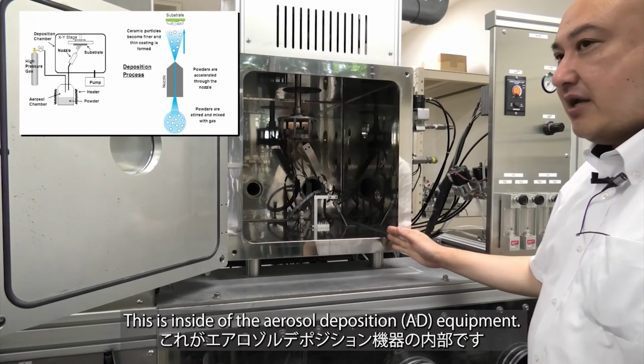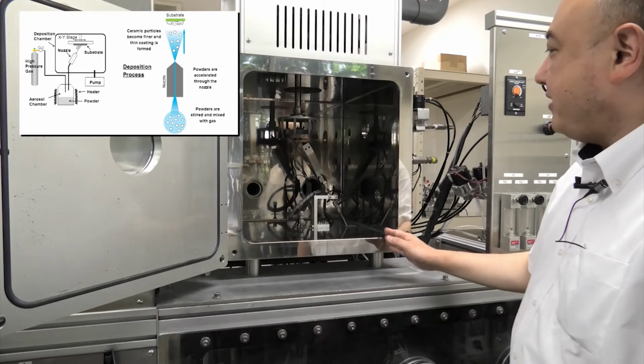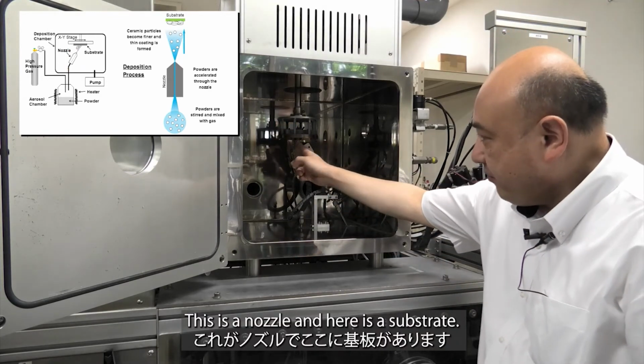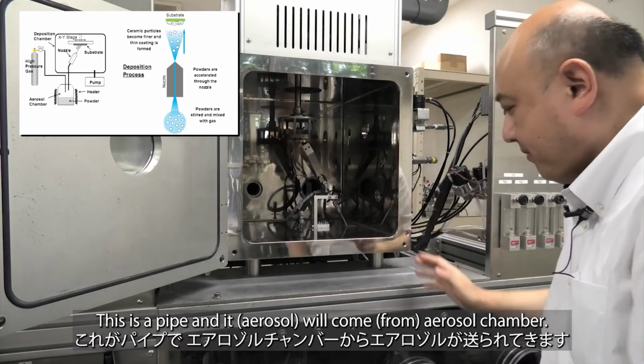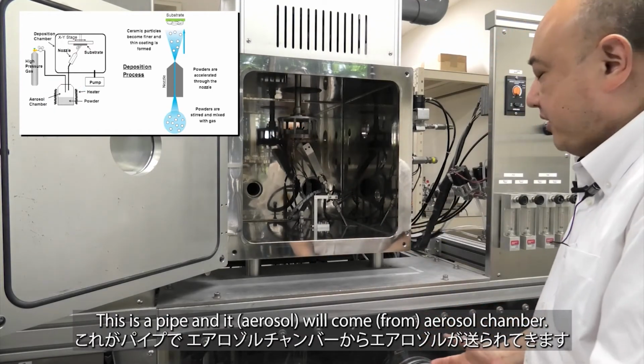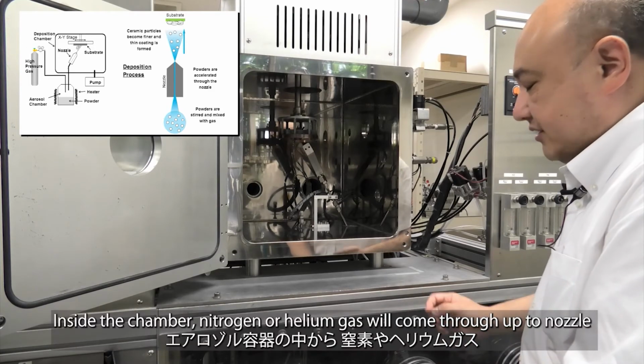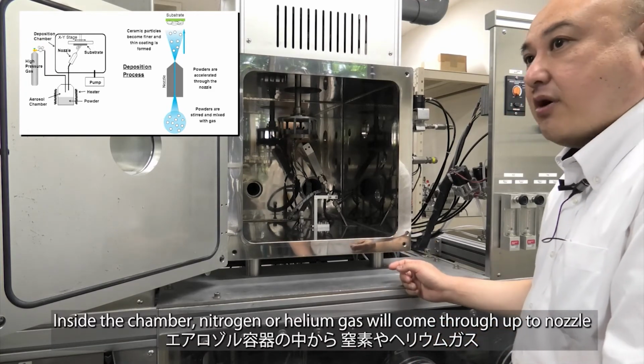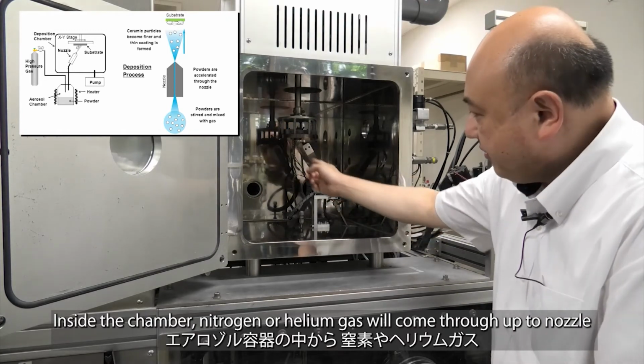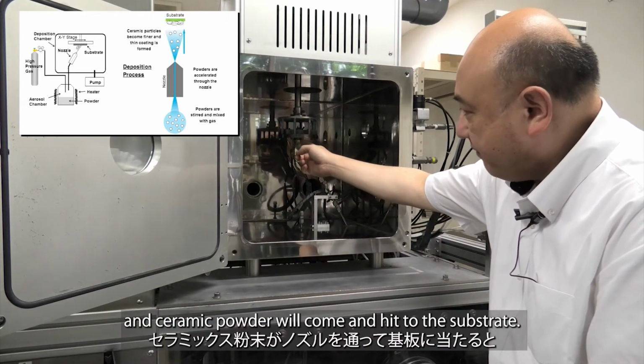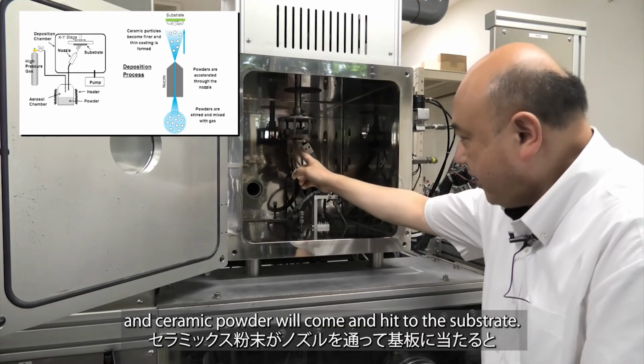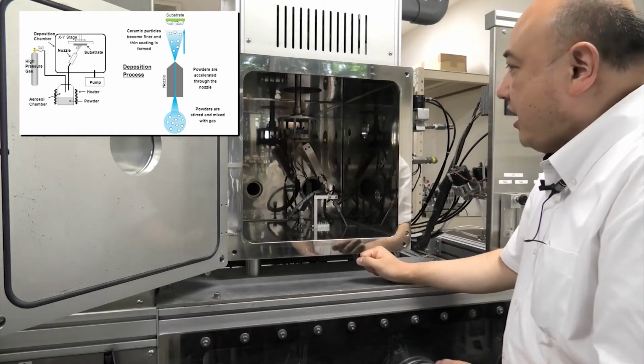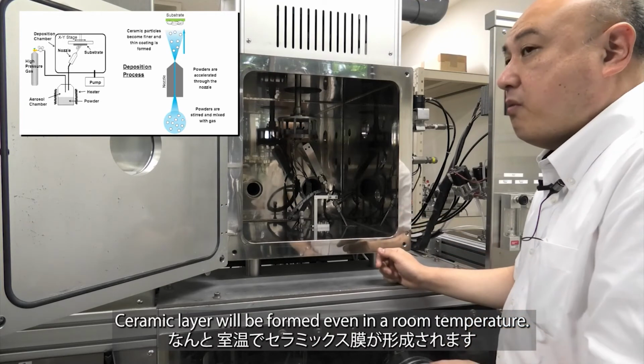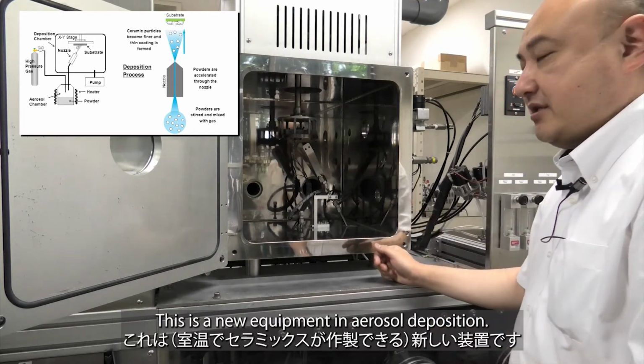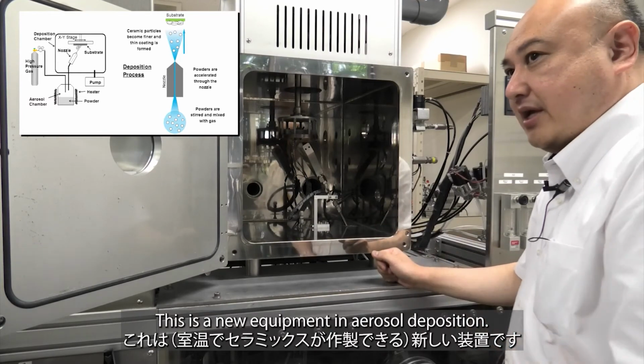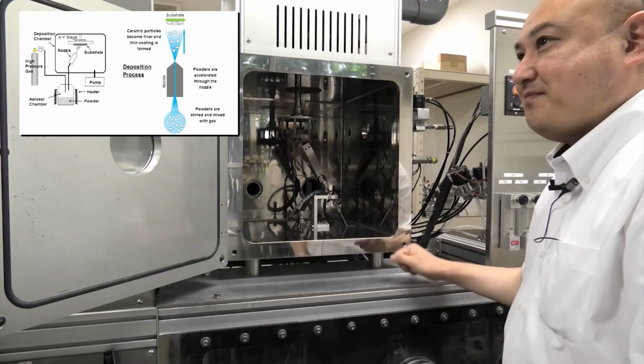This is the inside of the aerosol deposition equipment. This is a nozzle, and here we have a substrate, and this is a pipe. Nitrogen or helium gas comes into the aerosol chamber, goes up to the nozzle, and from here the ceramic powder will come and hit the substrate, and the ceramic layer will form even at room temperature. This is very new equipment in aerosol deposition.